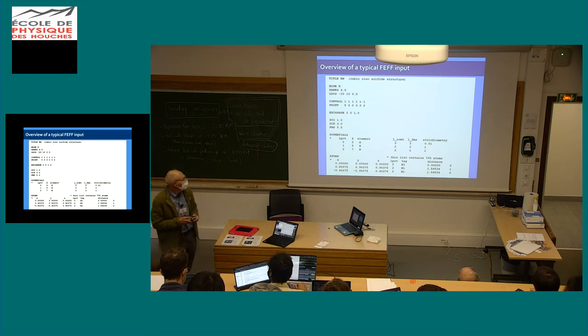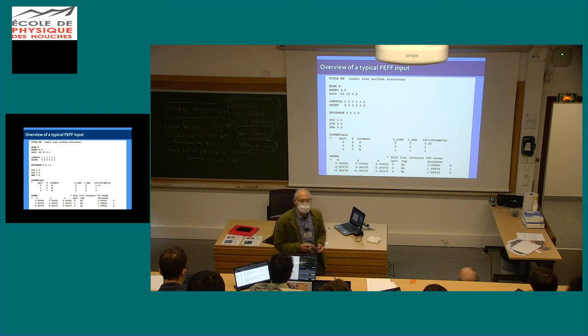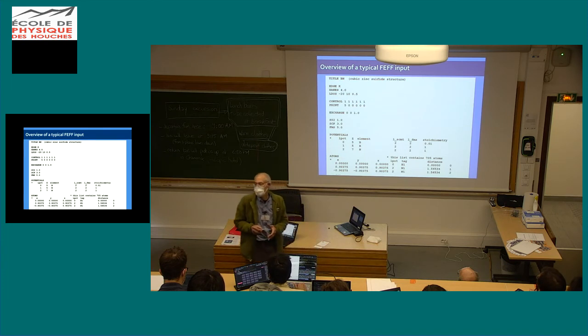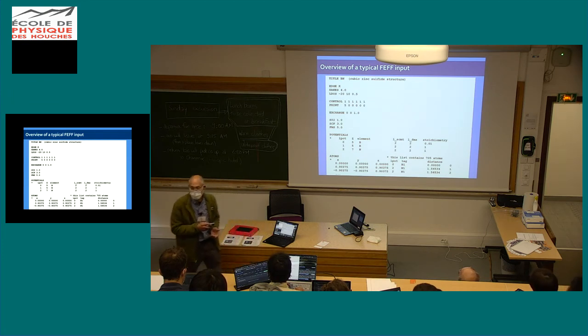John, what is the meaning of stoichiometry here? Okay, stoichiometry, this code is a little bit intelligent. Stoichiometry forces the charge counts on the boron and the nitrogen muffin tin spheres to be 1-to-1. So there will be a little bit of charge transfer in the self-consistent calculation, but you can impose stoichiometry, like if you have a nice crystal, and that'll give you stable potentials.